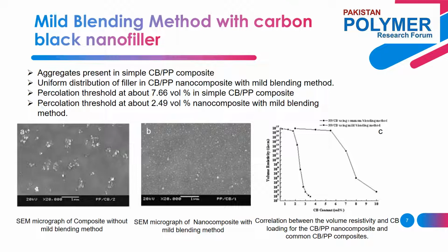At higher carbon black content, the scale of aggregation increased, which was caused by the connection of carbon black aggregates. The morphological feature of the carbon black and PP nanocomposite prepared using the mild blending method, as shown in figure B, displayed a different structure from the conventional carbon black and PP composite. It was observed that carbon black particles were detached from each other at the nanometer level with a homogeneous distribution in the polymer matrix.